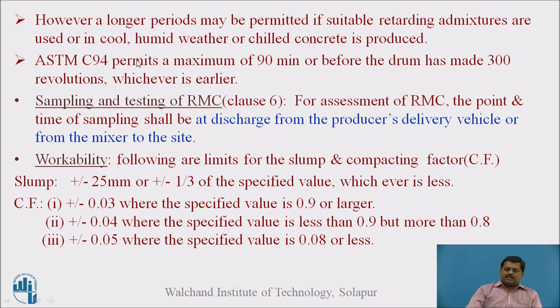In the case of time in transport, ASTM C-94 permits only 90 minutes, or before the drum has made 300 revolutions, whichever is earlier.